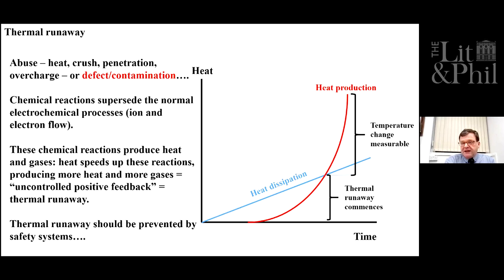One definition is essentially when we see a particular rate of temperature rise, 1 degree centigrade per minute, 1 degree centigrade per second. And that occurs when the rate at which heat is dissipated, which is linear, the blue line, crosses the red line, the heat that's produced. In other words, heat is produced faster than it can be dissipated, so we see a measurable temperature rise. But a far better definition of thermal runaway is when those exothermic heat-producing chemical processes become self-sustaining.